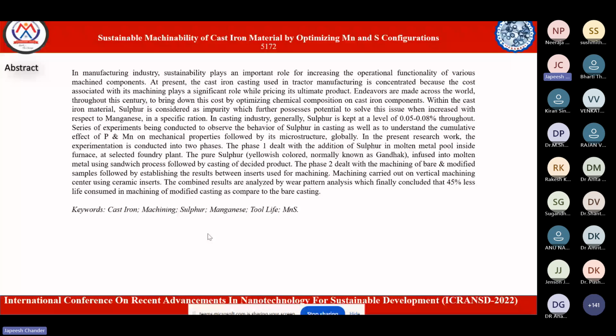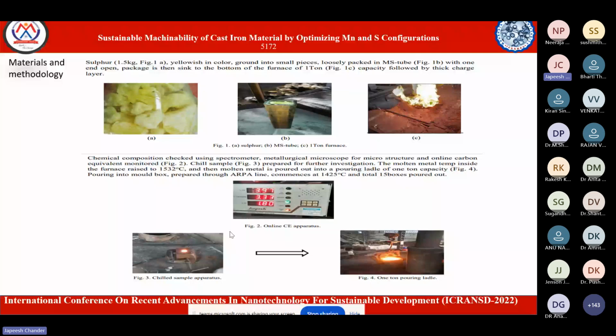When we increase the sulfur, we also increase manganese in the proportion so that it becomes manganese sulfide. Manganese sulfide is not a metal. It is not hard. It is a powder-like material. When sulfur combines with the manganese, it gives rise to manganese sulfide and gets embedded in the metal lattice. It is not visible from the outside. When you put the metal under the microscope, you will see small flakes, similar to graphite flakes.